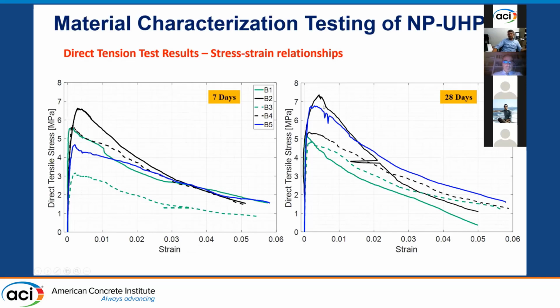You can see that in tension, it's not like compression. You don't really get a lot of change. So between 7 days and 28 days, the increase in the tensile strength was, I think, 20% or so, which is expected and matches what we have seen in the literature, because the tensile behavior has a lot to do with the steel fibers as opposed to the UHPC itself or the cement.